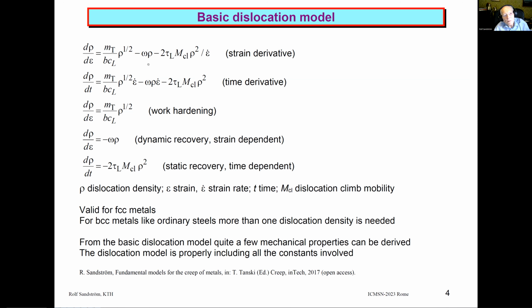When you add this, you get a strain derivative or time derivative for the dislocation densities. These formulations are fully equivalent. This approach is valid for FCC metals. For BCC metals like ordinary steel, the situation is a little bit more complicated because you often need more than one dislocation density. The important thing to recall is that all the parameters here and the equations are derived from physical principles. So it's a well-defined model.